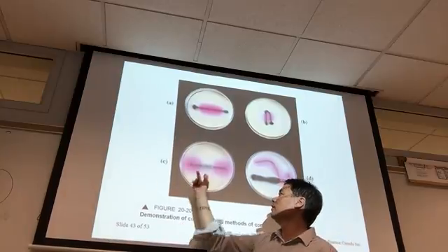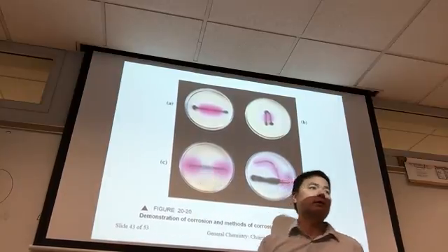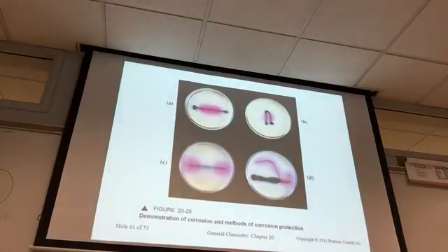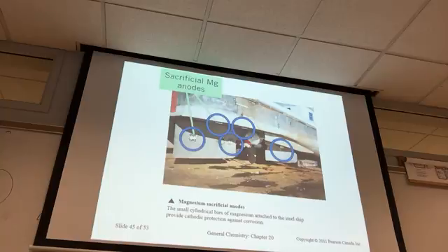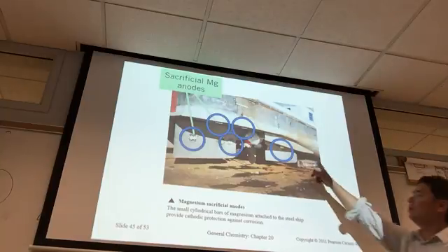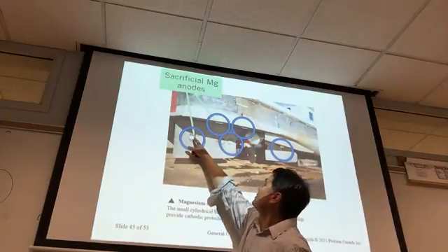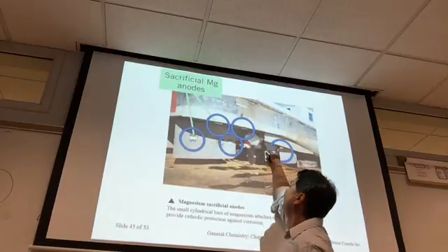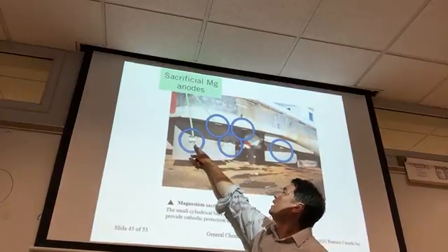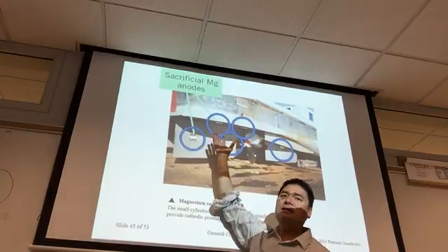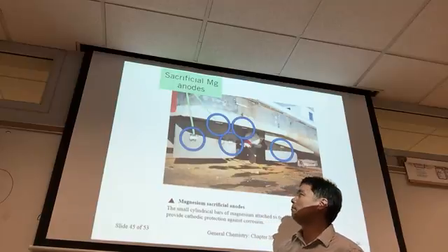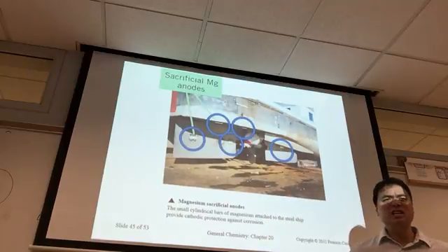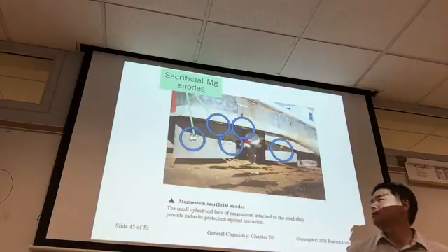We can use any metal that's more active than iron to protect it. And so ships, for example, ships are made of iron hulls, let's say, and these are sacrificial anodes that are connected to the iron. And this sacrificial anode is magnesium. Magnesium has a much higher oxidation potential than zinc, even. So magnesium is actually kind of dangerous because it's quite flammable.